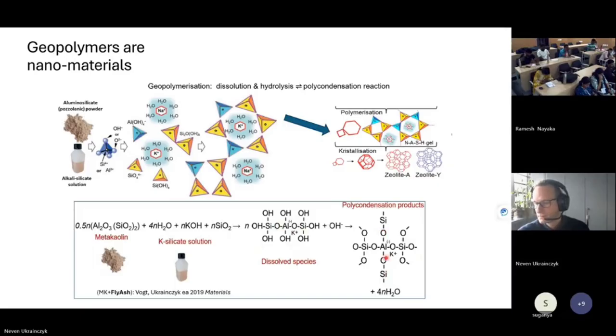And this goes into a big three-dimensional network. And what I told you here, we have the aluminate, which is negatively charged. And this negative charge of aluminate is compensated by alkalis. So these alkalis are bound to these aluminates by ionic bonding. And this is important because with acid attack we have leaching of these alkalis, and that's why I'm explaining this, because it's also important for the pH for the reinforcement. If you want to use it, then this pH goes down very fast, by leaching or by acid.